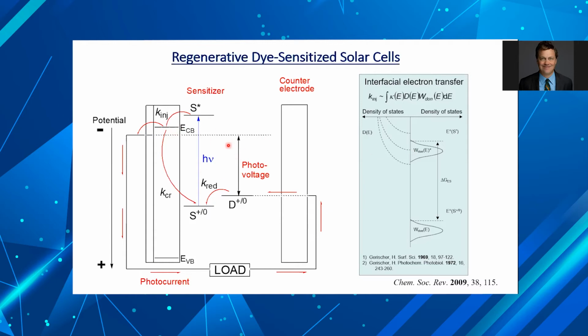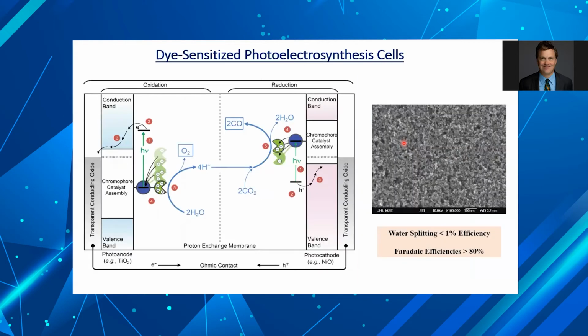In acetonitrile solutions, the presence of Lewis acidic ions like lithium can have a big effect on those. And one of the challenges of the field is that we often don't know where those acceptor states or conduction band states are in energy. The methods that Gerischer used to determine them at single crystal surfaces are often not applicable to very small nanometer-sized particles. So this is a challenge to understand this overlap. And I'll show you a little bit of that later in my talk.